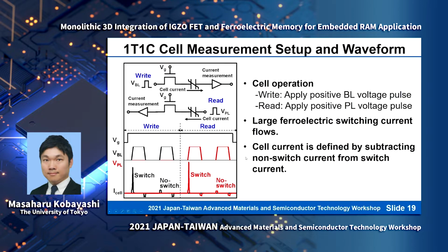And next, we're going to share the results of the 1T1C memory cell characteristics. We use a very simple pulse write scheme, and we also use a pulse read scheme to read the 1T1C memory cell. For the cell current, we define it by subtracting the non-switching current from the switching current, so that we can extract the intrinsic ferroelectric polarization charge current.